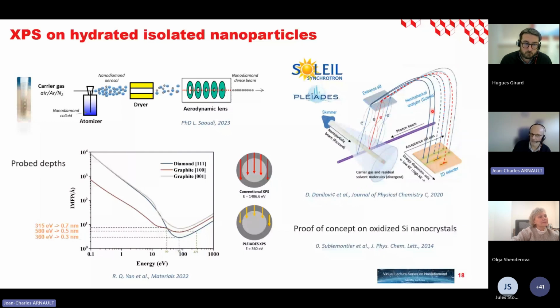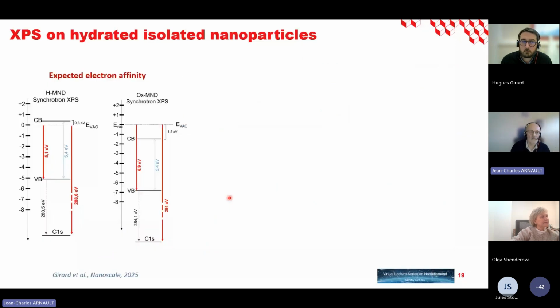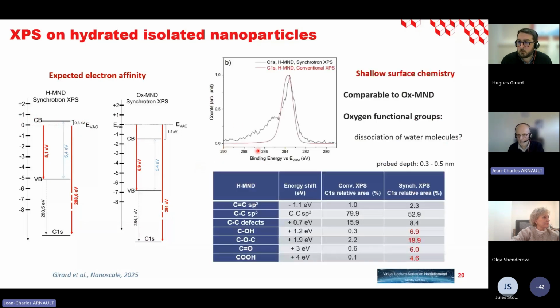So this is XPS on hydrated isolated particles, as you will see. And of course, compared to conventional XPS, due to the tunable energy of the photons, you can probe a very shallow surface. In this study, we probe between 0.3 and 0.5 nanometer. What are the results? First, we obtain the expected electron affinity for both particles. For the hydrogenated MND, we still have the negative electron affinity, while it shifts to positive electron affinity for the oxidized particles.